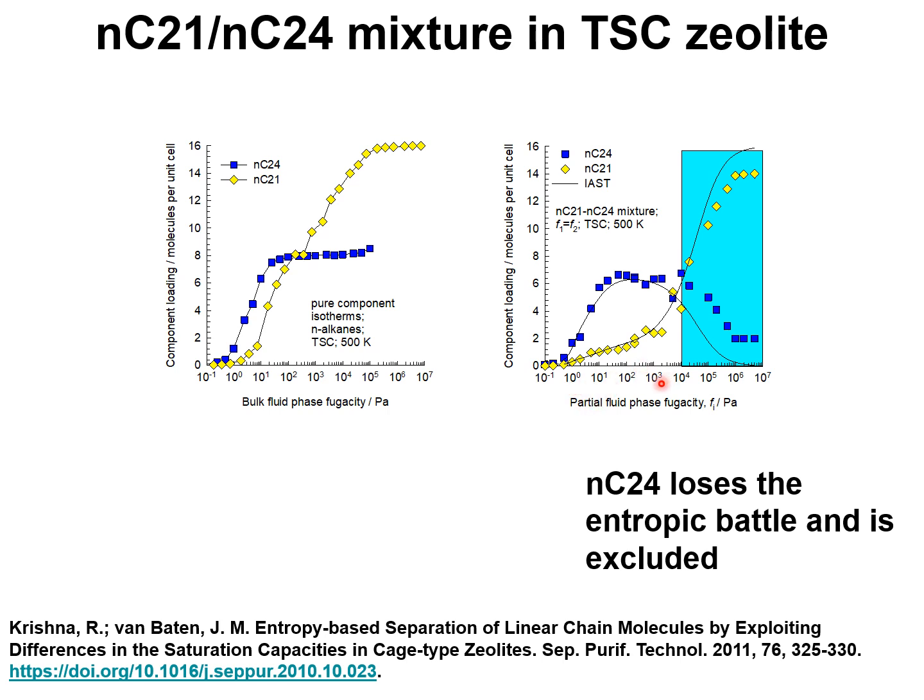For operations for mixture adsorption at fugacities in excess of 10 to the 4 Pascal, which corresponds to feed mixtures in the liquid phase, the mixture adsorption equilibrium is in favor of the alkane with the shorter chain length, and entropy effects exclude the adsorption of the alkane with a longer chain length, because the longer chain alkane loses the entropic battle.